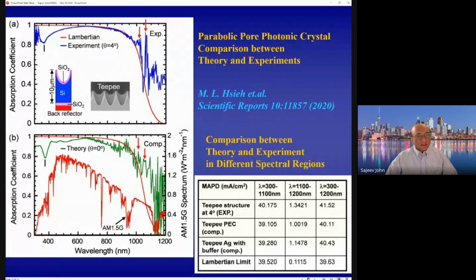The red curve shows the Lambertian limit as a function of wavelength from 300 to 1200 nanometers. And the blue curve is the actual experimentally observed absorption coefficient. So you do in fact see these absorption resonances at these long wavelengths. And below that is the green curve, which corresponds to the calculated absorption spectrum, which likewise shows these absorption resonances. This is the AM 1.5 solar spectrum superimposed below it. The theory was done at normal incidence. The experiment was actually done at slightly off normal incidence.